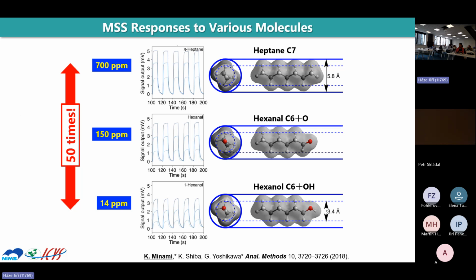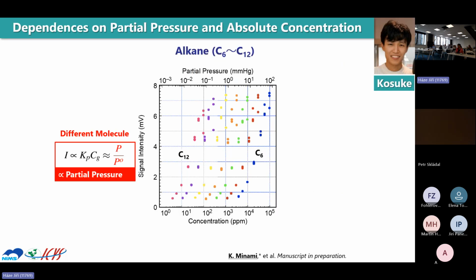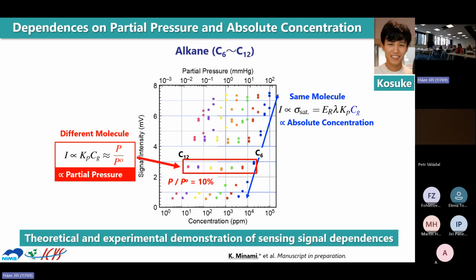So in this case, for different molecules with similar lengths, the saturation concentration is more than 50 times different. But still, the sensing signals are almost the same, at least in the same order. So actually, this is understood by analytical modeling, and this is in the case of alkanes. And anyway, the sensing signal is proportional to partial pressure.